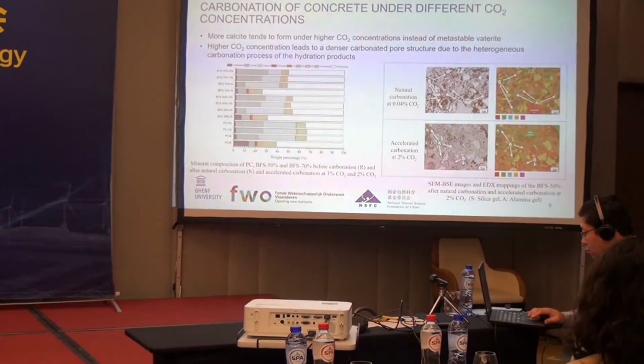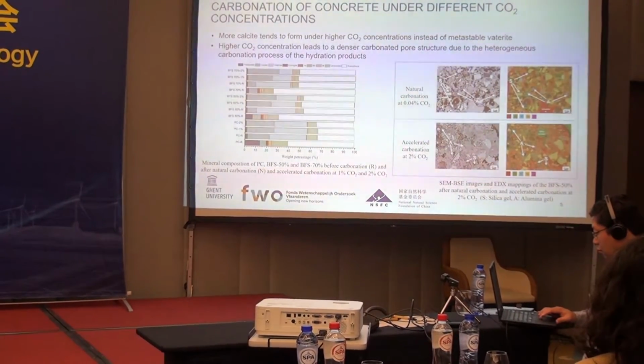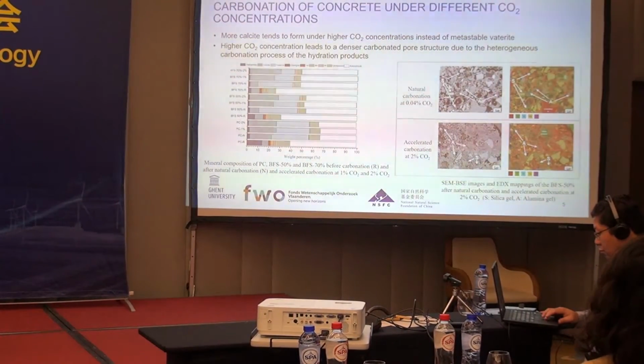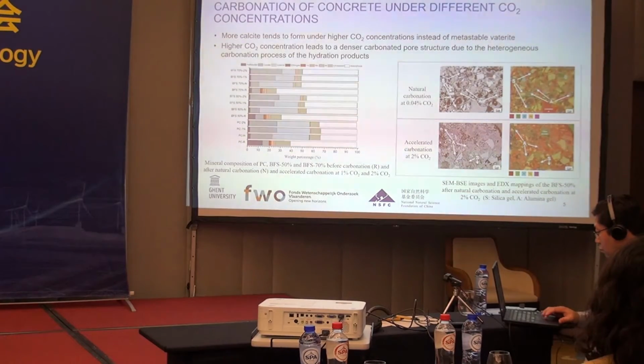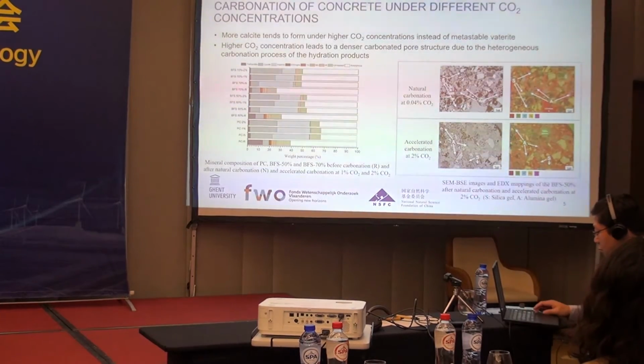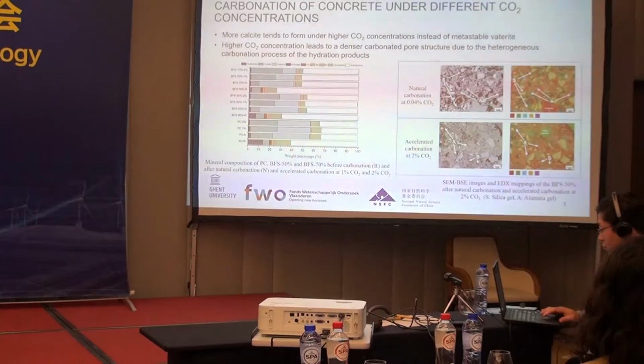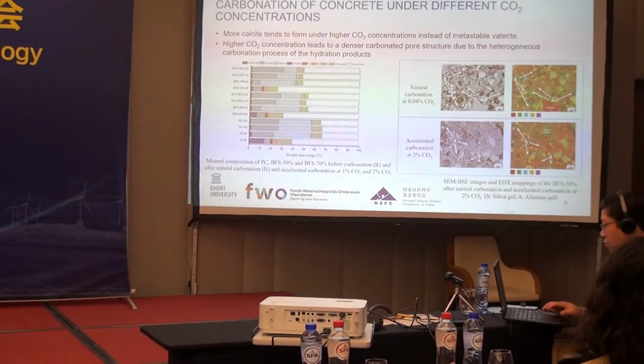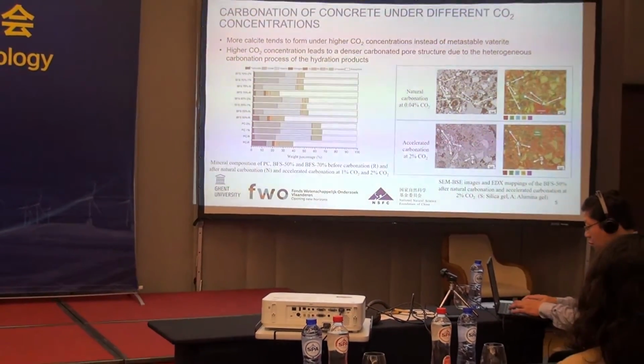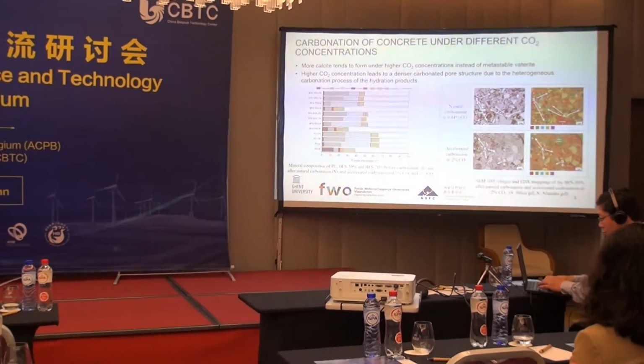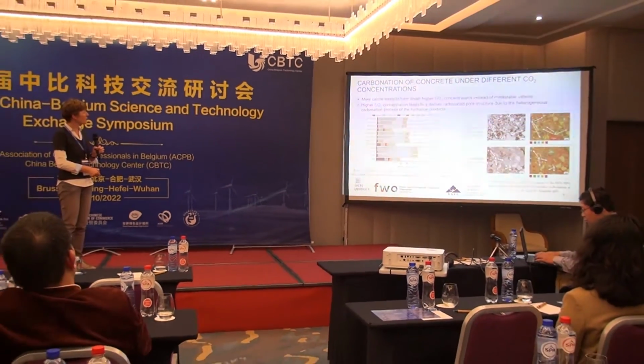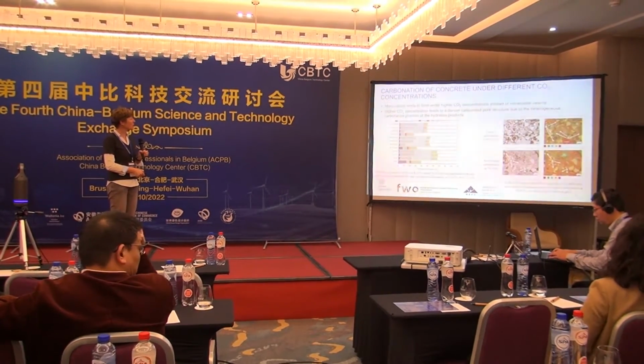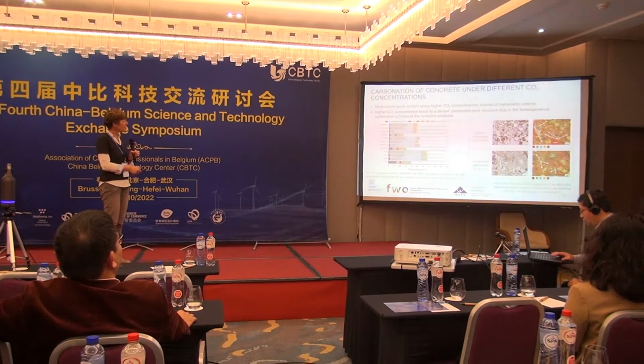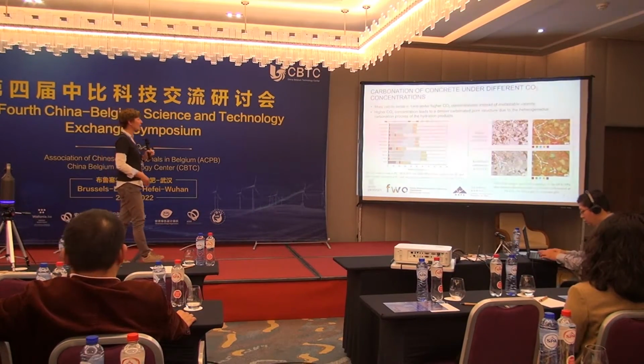For instance, he has been analyzing the mineralogy of the products present in concrete with different percentages, for instance, of blast furnace slag in the normal Portland cement concrete, and then with 50 or 70% of the Portland cement replaced by blast furnace slag. And then he analyzed what is happening if you carbonate under natural conditions or at 1 or 2% carbon dioxide for these different compositions.